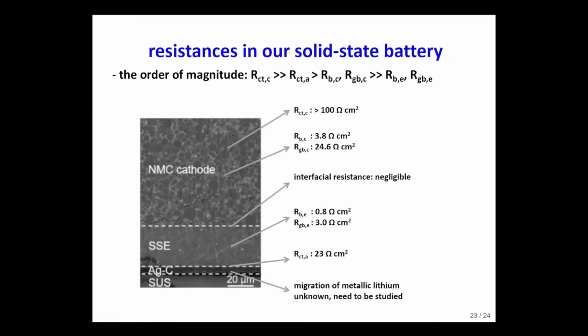Okay, here's the summary of this work. You can see that the charge transfer resistance in the cathode is the dominant one. Also, the charge transfer resistance at the anode and the grain boundary resistance of the electrolyte inside the cathode are important factors. We cannot move away from them when considering polarization decrease. Those three resistance components should be significantly improved to get a good rate performance in solid state batteries.